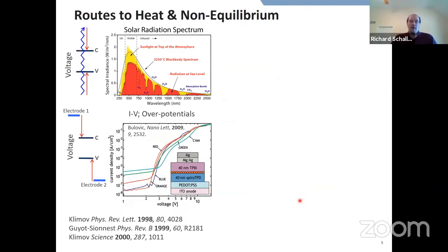Okay, so just talking about carriers and creating phonons, in some cases, even when you might think of an application as being DC, where it's just a constantly on device, you have non-equilibrium phonon creation just from the fact that a photon is absorbed at some instant in time, even in a solar cell. Your carriers may initially be up at high energy, but those electrons are going to fall down to, say, the conduction band minimum. A hole, which is the absence of an electron, is going to move up into the valence band maximum. And so anytime you absorb photon energy that is in excess of the band gap, you create thermal energy.